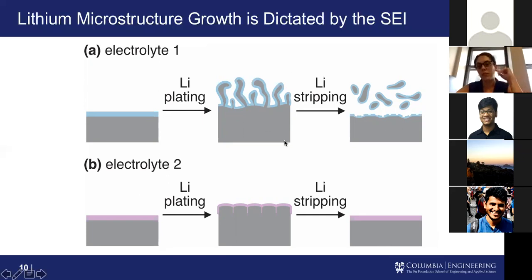You also see things like a loss of efficiency in the battery. When you have these dendritic structures and you try to remove the lithium from this, so you try to strip it back off and get this lithium back out during discharge so that you can make this battery rechargeable, it actually doesn't work so well. It doesn't want to come out in a homogeneous manner if the SEI isn't very good.